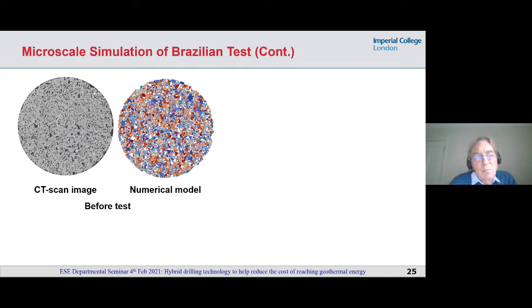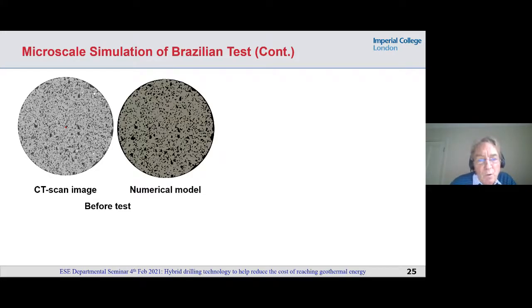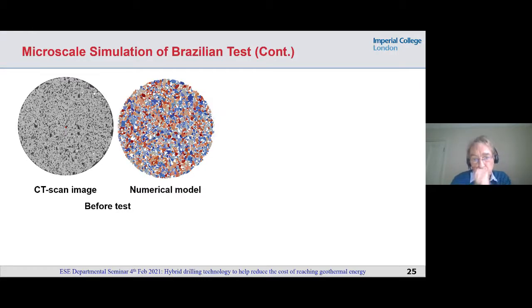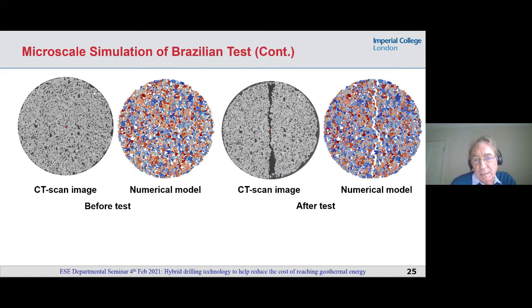So let me just show you a comparison of the CT scan image and the numerical simulation here. That's our numerical model shown in multicolored grains. That's the same numerical model in binary, and you can see how beautifully similar it is to the CT scan. It is actually developed from the CT scan. And then on the right hand side, we can see this CT scan and how it broke in tension effectively. Our numerical model gives a slightly more tortuous crack path, and this is easy to explain.